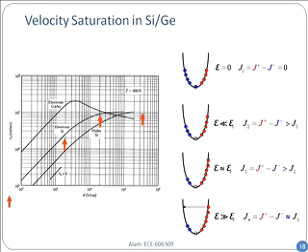So what happens beyond a certain point, after scattering, the reverse going one catches up with the one that is going in the forward direction. So beyond that point, the net flux doesn't change. Things get frozen in the proportion of red and the blue one. It cannot do anymore. You can see the black arrow I have shown for the red electrons. That is to indicate that at high field, constant scattering back essentially creates two streams which are one optical phonon away. And these two streams, the proportion of it cannot change. And as a result, current cannot change, and the whole thing saturates.